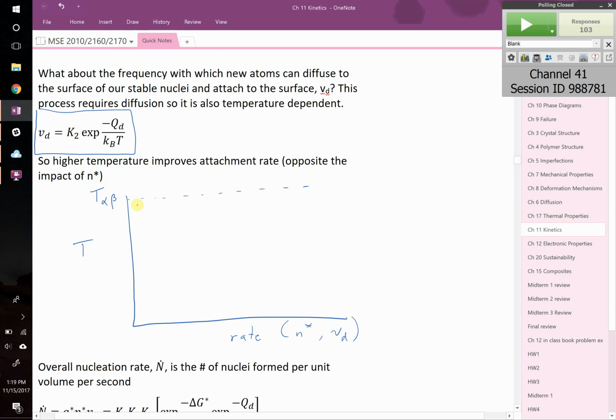The lower you go in temperature, the more of them there should be, right? Because the lower and lower you go, the activation energy to form these nuclei gets smaller. Or in other words, the critical nuclei size gets smaller and smaller the further you go below that. In other words, we can't infinitely supercool this water. If we keep on supercooling it, eventually we're going to have so many nuclei, it's just going to crystallize. But that may not be the fastest way to crystallize it because we have to consider attachment. And attachment is going to mean that you need thermal energy for these water molecules to find their way to the ice crystal. And that does the opposite.